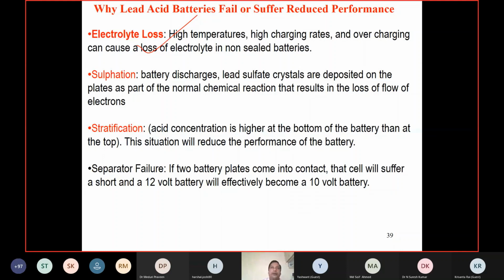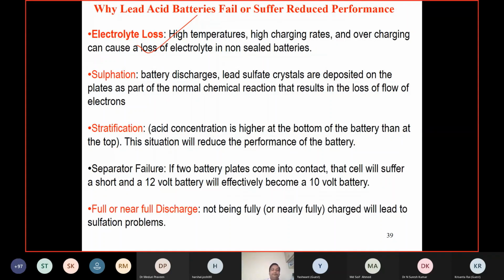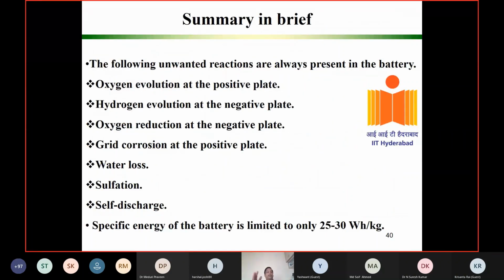If concentration is very high at the bottom, then what will happen? You will have more lead sulfate formation. More lead sulfate formation will cause significant capacity loss. And in some cases, separator failure, though that is very rare in general. And then we should always keep the battery in the fully charged condition, not the discharged condition. Discharged condition will lead to lead sulfate. Lead sulfate formation is the biggest problem in the lead acid battery. How to reduce lead sulfate formation? These are the important areas you can work on for the lead acid battery.